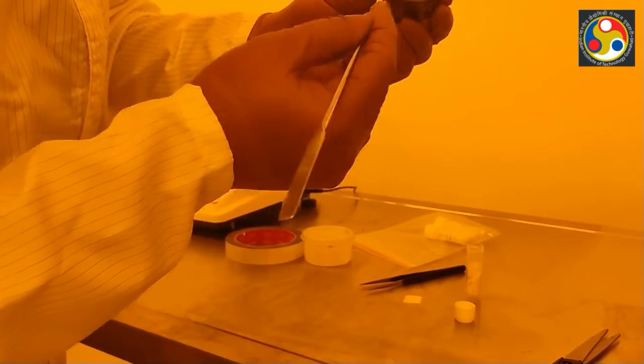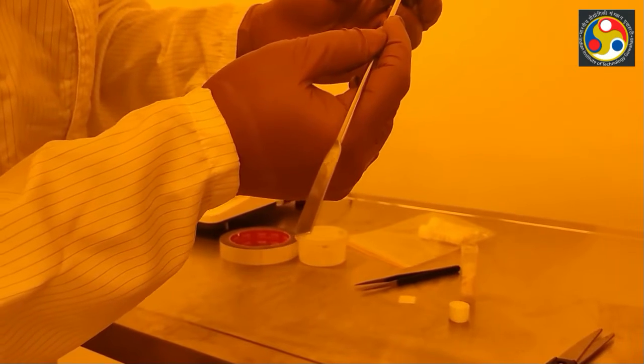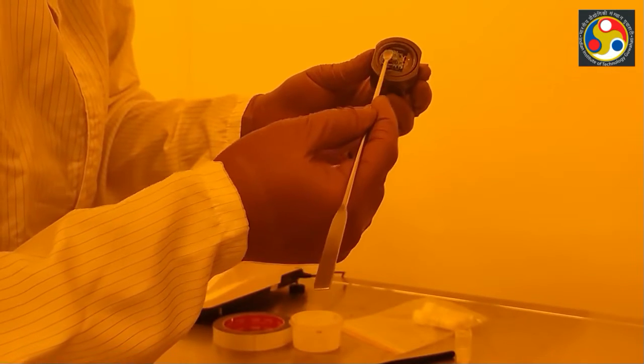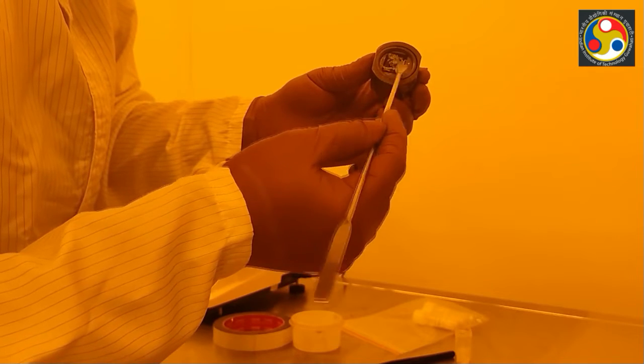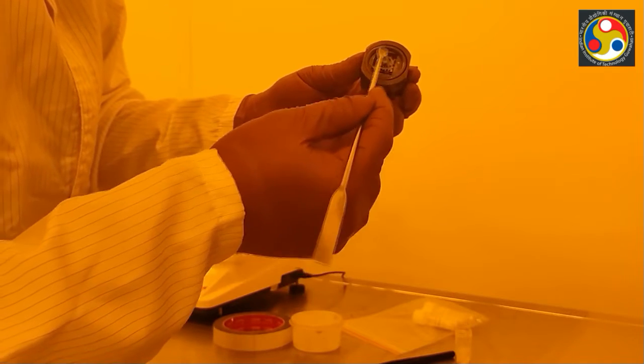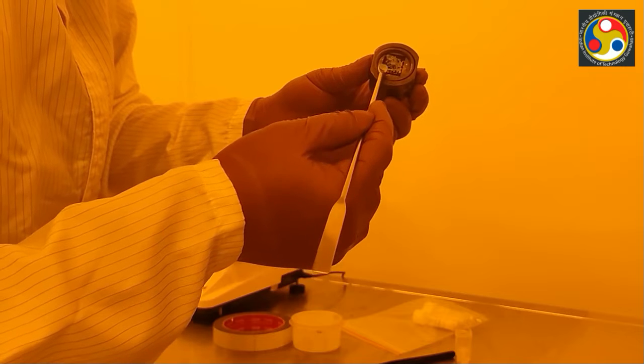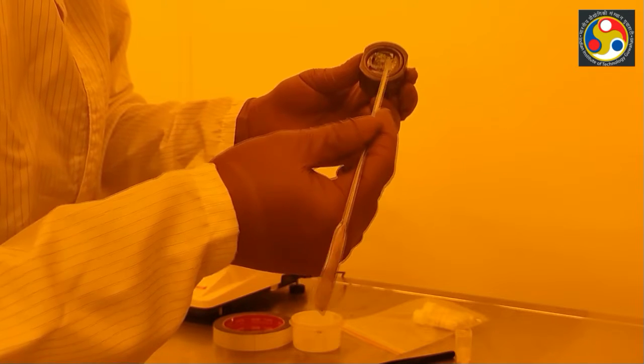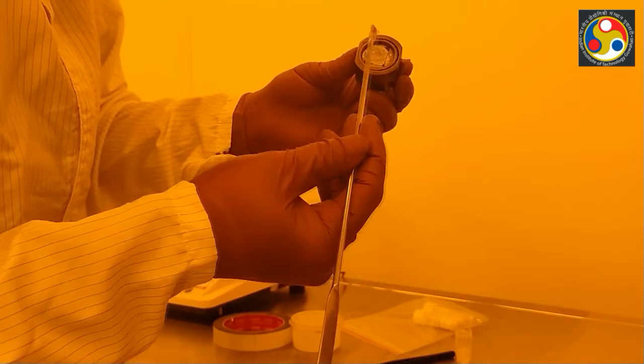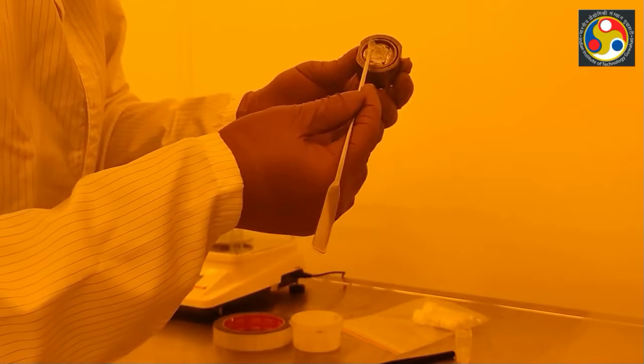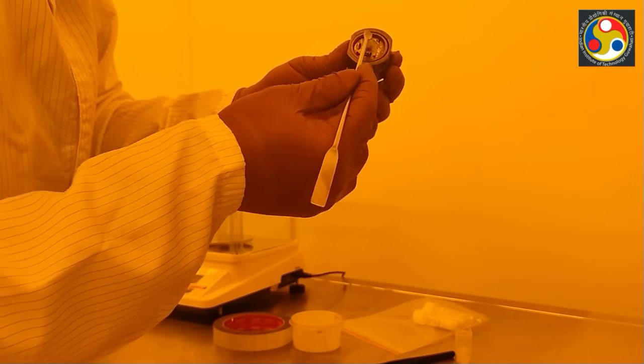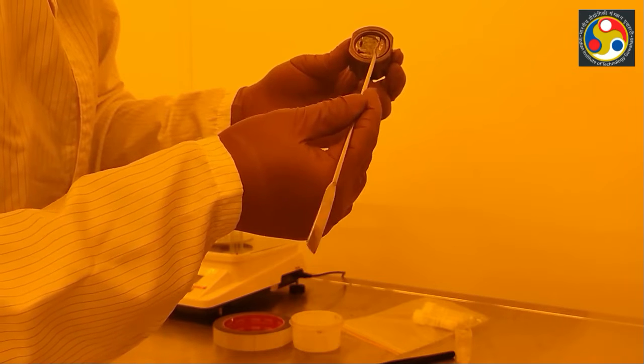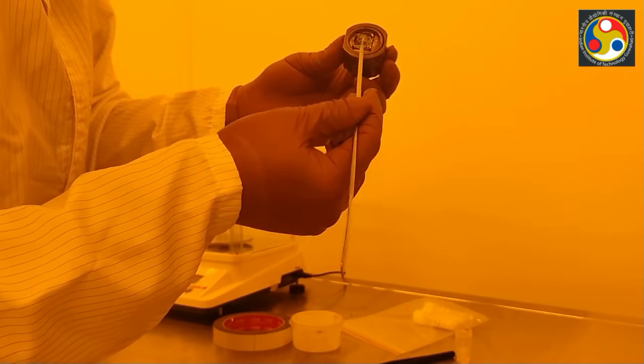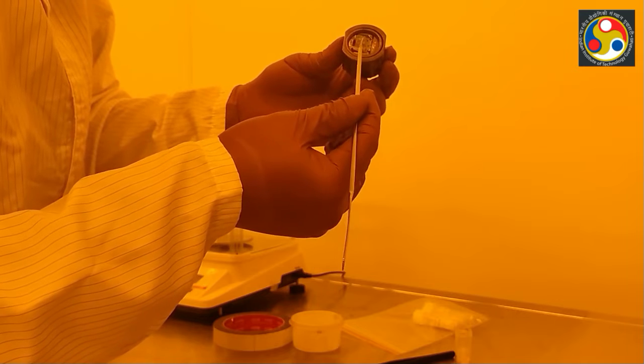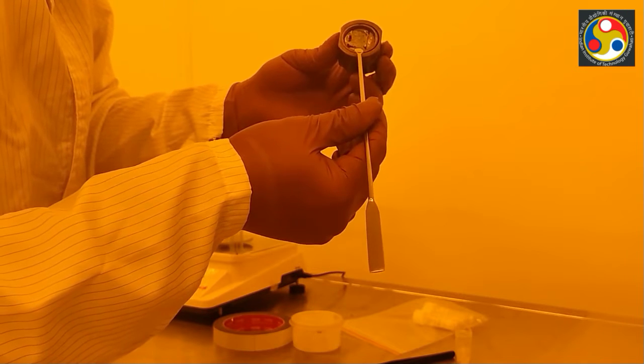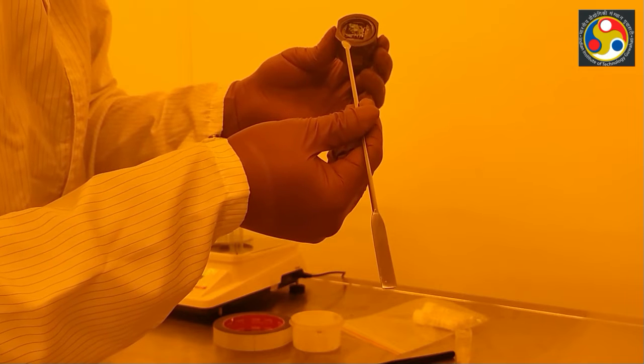Because this sample holder is very big and I have only one sample, I took a bigger carbon tape and spread my material all over it. You don't need this much area of carbon tape and this much material for normal analysis, but for the sake of showing, I am just taking it like this. So the material is being deposited, spread on top of this carbon tape, which is pasted on the sample holder. Now this carbon tape is adhesive on both sides, so it can stick the material and it can stick itself into the sample holder also.